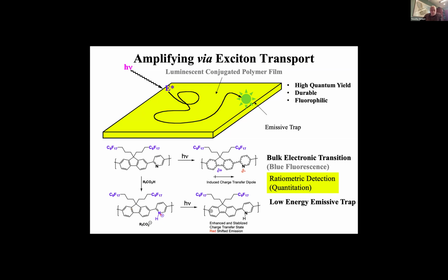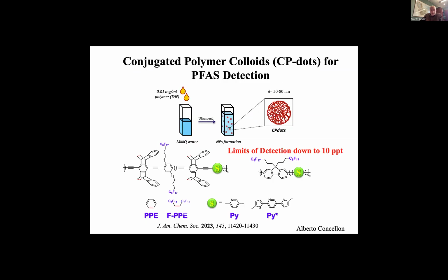And that proton protonates the pyridine ring, and that shifts what we call a charge transfer electronic transition to the red. That creates a red shift in the emission, which gave us that color change that I showed you before, and I'll show you again here in a moment. Now, we've done this a number of different ways.